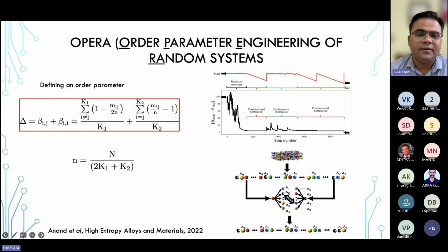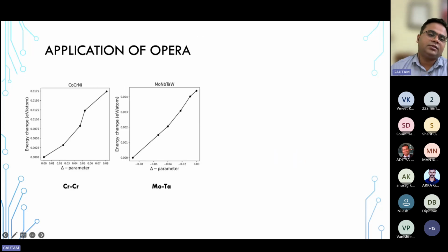We have applied this approach to generate the short range order structure in a medium entropy alloy. Say in this case, chromium bond propensity is increased. This is a like bond, so the delta parameter is positive. As you can see, if you put chromium together, the energy of the system increases.